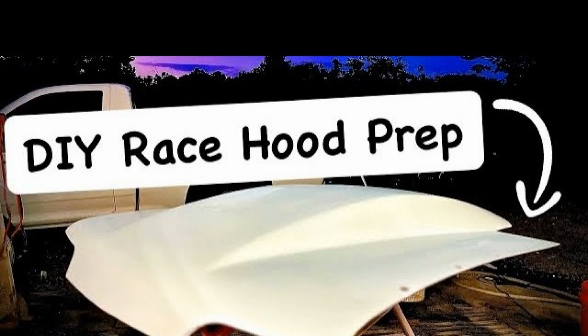Apply gel coat. Note that it cures fairly quickly, 7 to 10 minutes. After curing, when touching your finger will not cause the material to peel off, you can apply another layer. Try to stretch the gel coat as evenly as possible. Leave the surface for 12 to 14 hours for complete drying.